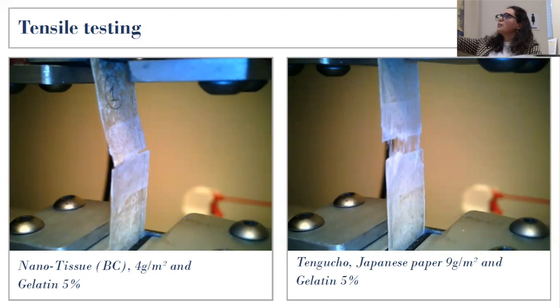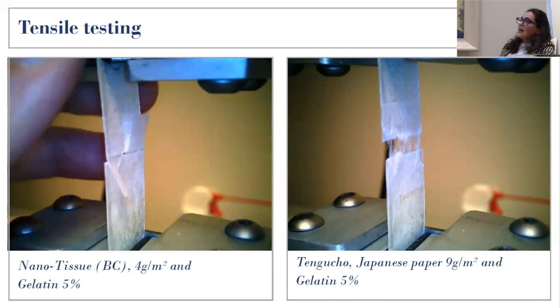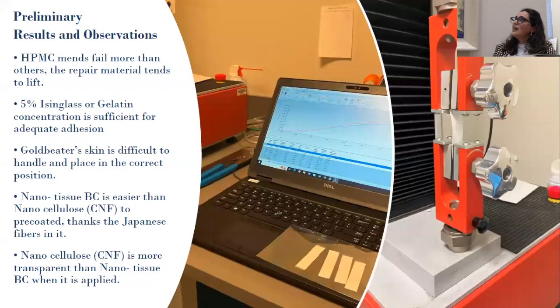In both cases, the mending material breaks in exactly the same position where the previous tear was made, but in one case the break is clean, and in the second case the instrument is just pulling apart fiber by fiber of the Japanese paper. Next slide, please. And in these two cases, we also noticed a third case where the mending material simply lifted. In this case, what failed was the adhesion of the material on the parchment support. Next slide, please. So now we are in the process of comparing all these results.